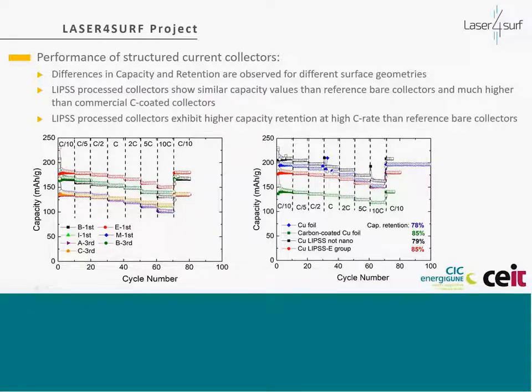So it is important to remark two things here: mainly the capacity, so the initial value here, and also the capacity retention, the ability of the cell to recover the initial capacity that it has before it starts to be cycled. You can see here that depending on the processing conditions, we can get different curves for charging and discharging, and for the capacity and capacity retention. The best one here is the one marked in red, the one corresponding to sample E, that has very good capacity retention and very good capacity values at the start of the cycling process.